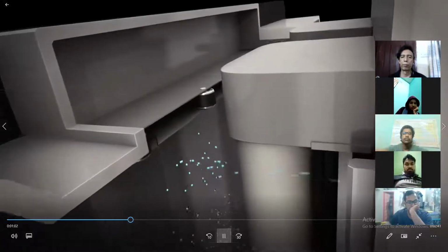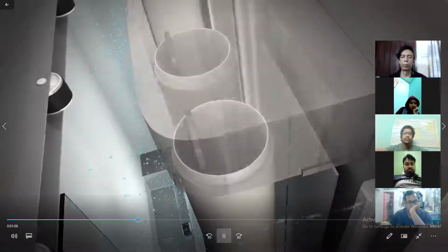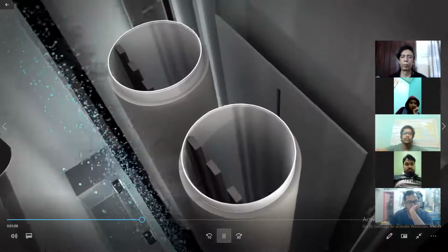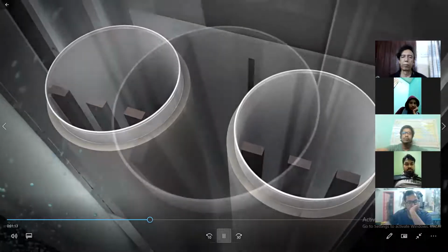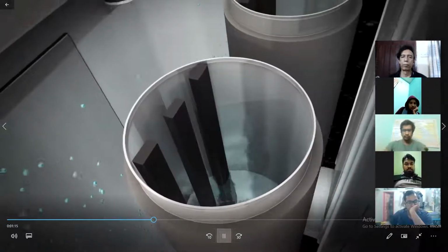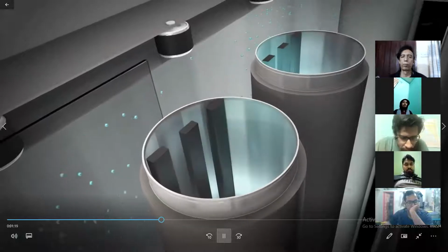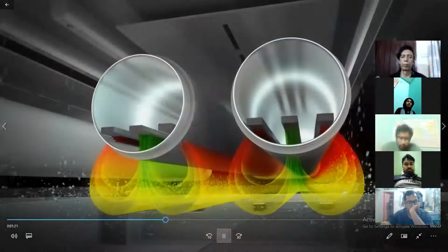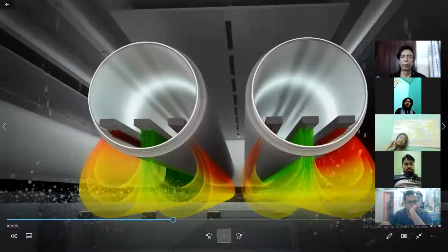Argon gas is introduced continuously to achieve a low-pressure argon atmosphere. A magnet array inside the cylindrical target generates a magnetic field. The target is filled with cooling water, which will dissipate the heat generated during the sputtering process. The targets are rotating so that the material will be utilized uniformly.